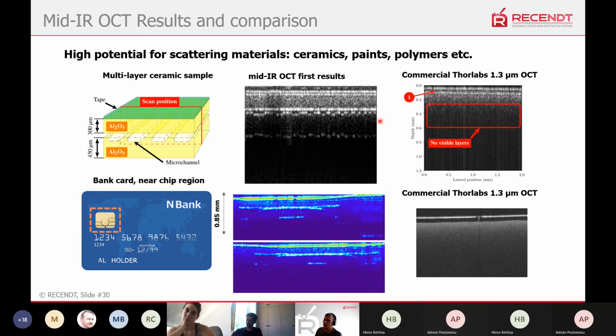Yeah, coming to the results, these are the first results. This is the very first result for the sample. Actually, it's very interesting that this sample was shown before. Rongsu performed simulation for this sample, and with this measurement we could confirm that at 2 microns we could see through this ceramic sandwich. So it's 2 plates of quite scattering ceramics. And just for comparison, the commercial Thorlabs system at 1.3 could not even see this interface. The first plate is 300 microns and the second one is around 0.5 millimeter.